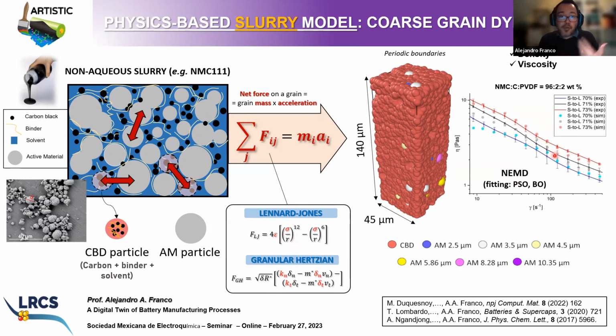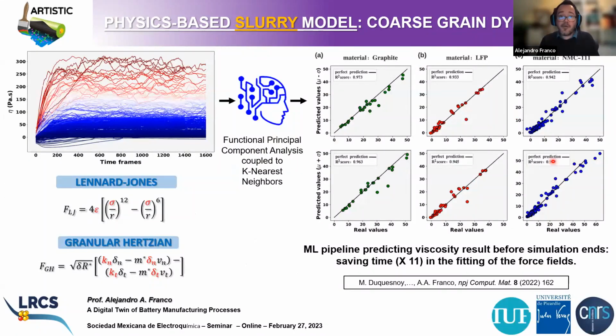And in order to do so, we fit the density values that we calculate with experimental ones, and we also fit the viscosity values that we calculate for different shear rates with experimental ones for different slurry formulations, different solid contents. And in order to fit the parameters, we adopt a combination of optimization techniques, combining in particular two techniques, particle swarm optimization and Bayesian optimization, but also machine learning, okay?